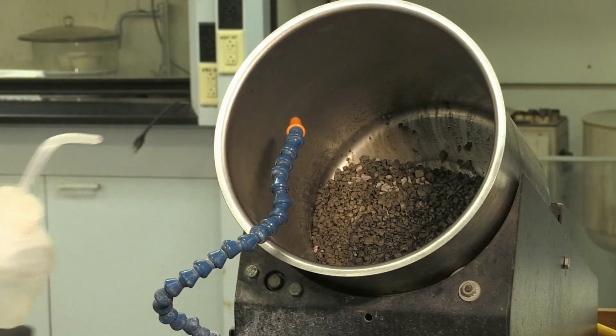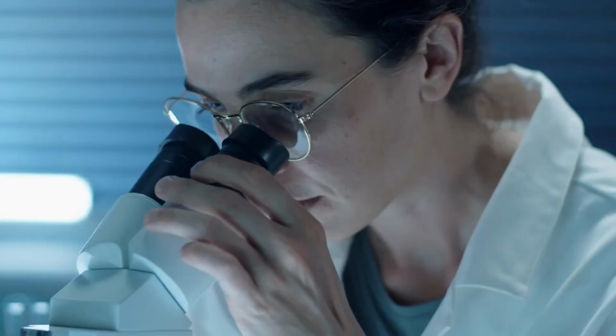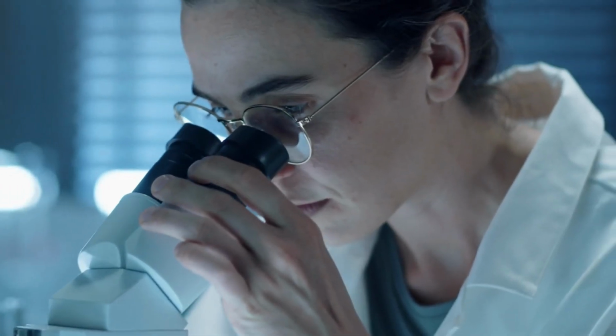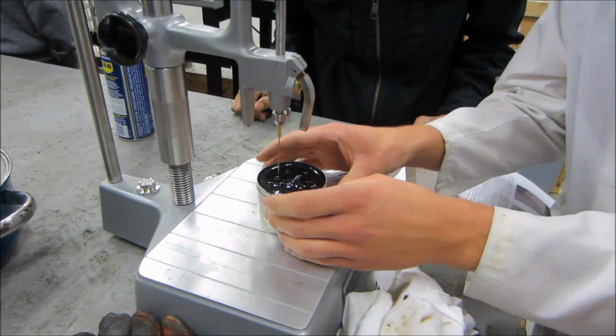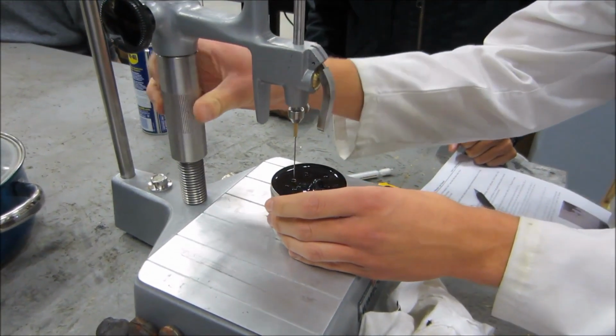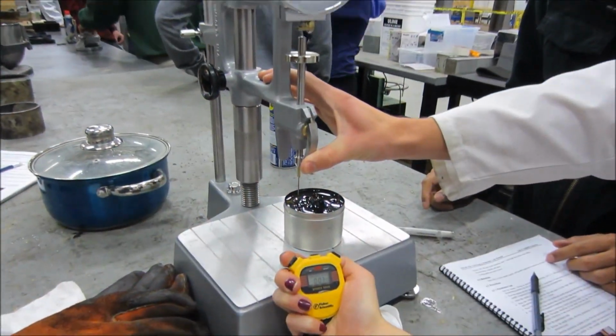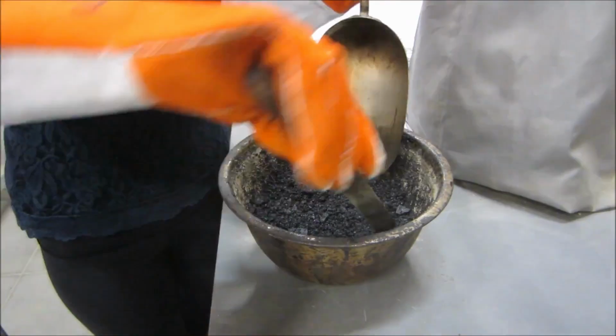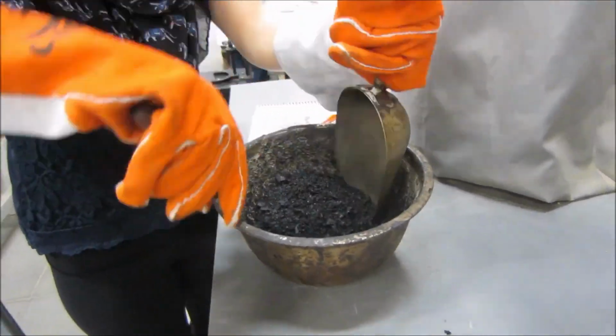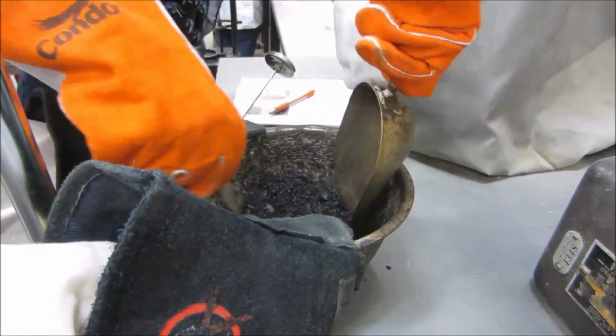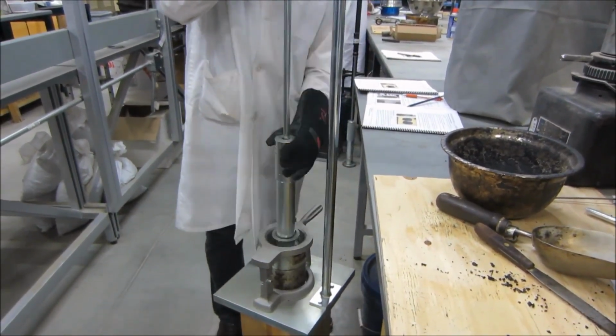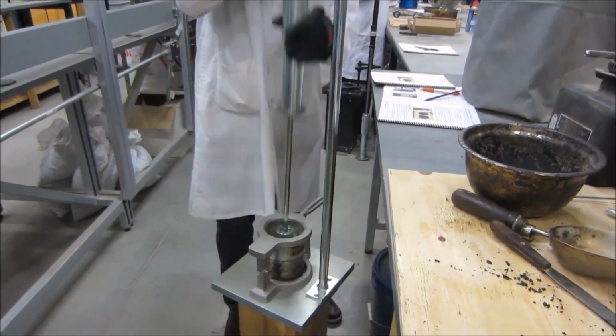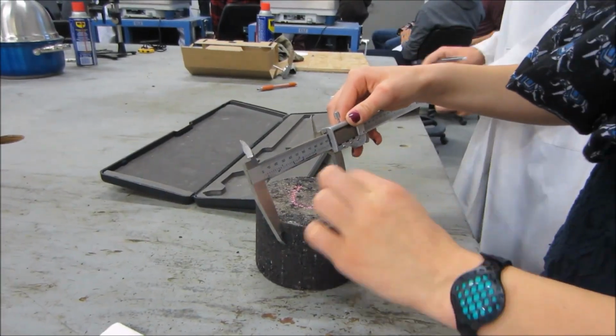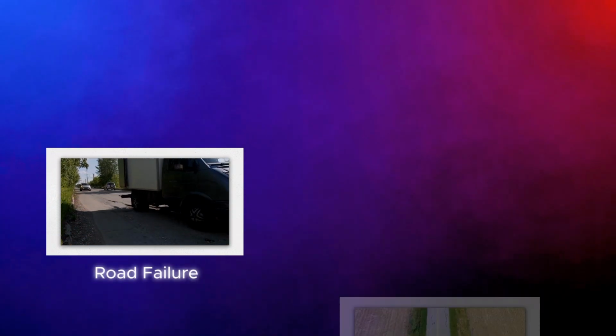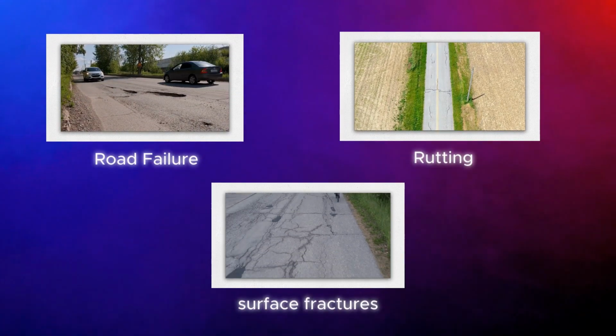Even the shape of the individual stones within the mix is examined under high-powered microscopes, ensuring they interlock perfectly when compacted. One of the most critical checks is viscosity. Bitumen must remain flexible enough to absorb stress without cracking, yet strong enough to hold its shape under immense weight. A slight deviation in this balance could cause early road failure, rutting, or surface fractures.